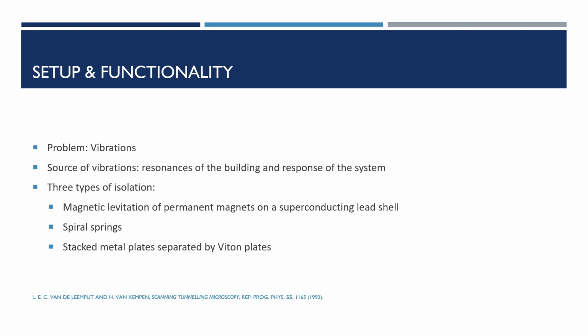There are 3 types of isolation which were used for the STM. The first STM used magnetic levitation of permanent magnets on a superconducting lead shell, but this method is no longer used today. Another method was to suspend the STM with spiral springs. These springs act like a low-pass filter. Up to the cutoff frequency, the STM follows the movement of the coil suspension. However, there was a problem that at the cutoff frequency a resonance occurs, which should be suppressed with the help of damping, for example an eddy current damping.